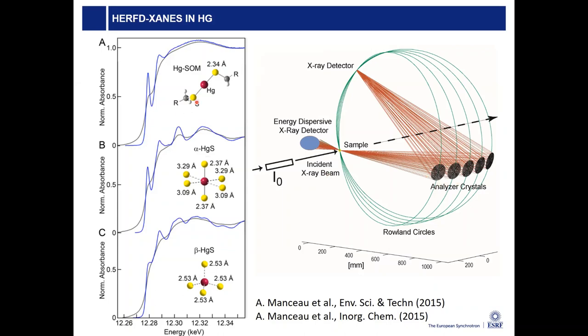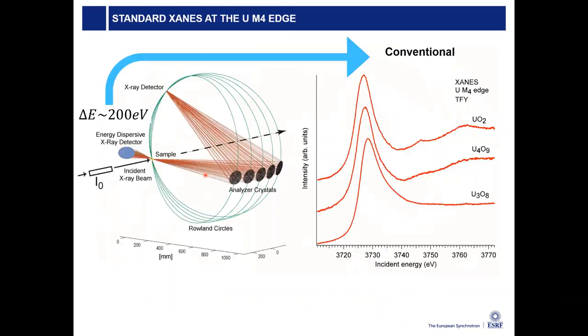And you see how you can nicely distinguish in the high resolution data between different coordinations of the mercury in this case. If you have linear coordination, you get this strong edge peak. If you have a six coordination, it becomes weaker, and it becomes even weaker if you have a tetrahedral coordination. So it's similar to the chromium. The edge spectral shape, highly resolved, allows you to identify the local coordination of the mercury in the system.